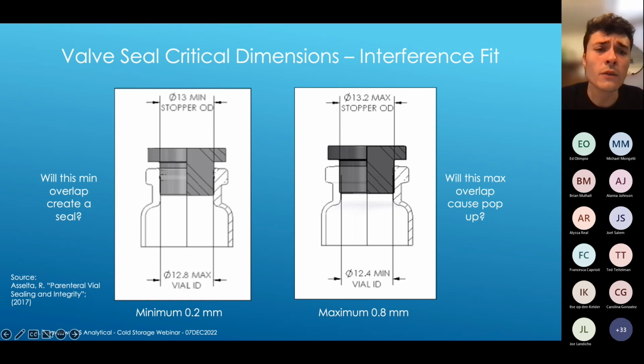And so for the valve seal, when we have the widest vial mouth inner diameter and the smallest plug diameter that are within the dimensional tolerances as established by the manufacturer, do these dimensional extremes yield a good seal? Is there enough overlap to create what we call an interference fit, such that the elastomer would be compressed against the opening of that vial mouth?